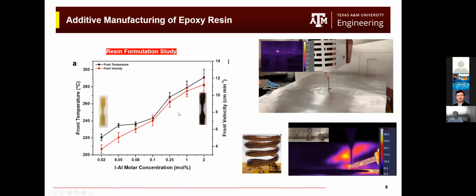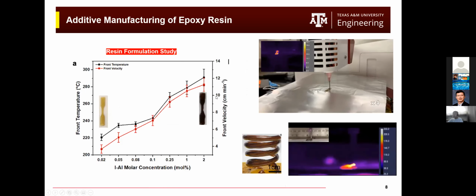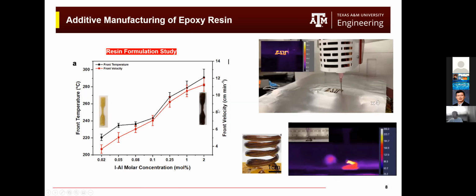So if we want to manufacture epoxy composites, the first thing we studied was the concentration effects on the frontal temperature. We think that by reducing the frontal temperature, we can significantly increase the part performance, and also make it compatible with the additive manufacturing process.